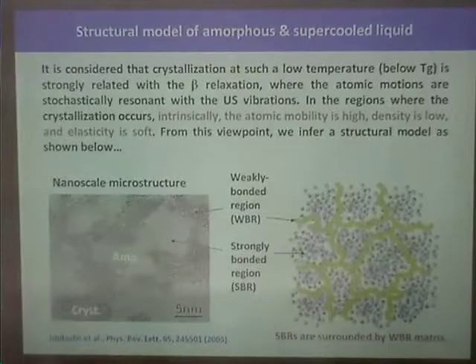I questioned your choice of intrinsicness of the phenomenon, because crystallization is a rare event, and it could be related to a local random fluctuation. It doesn't necessarily mean that the entire region is more mobile, because once you start crystallizing, you have a more compact phase that arises, and that itself can fuel the extension of the crystal. So it doesn't necessarily reveal that there is an intrinsic heterogeneity in the structure.